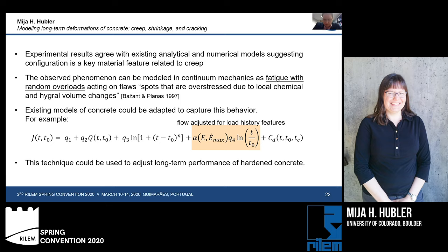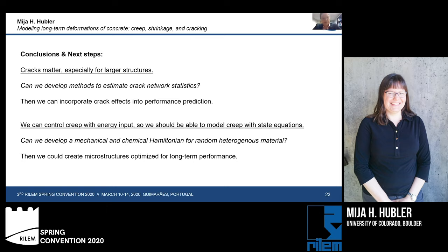So in conclusion, I'd like to summarize two things. First of all, cracks do matter, especially for larger structures. The next question that I'd like to pursue is whether or not we can develop methods to estimate crack network statistics so that we could introduce these better into our performance predictions. The second point I'd like to make is that we can actually control creep through energy input. So we should be able to model creep with state equations.